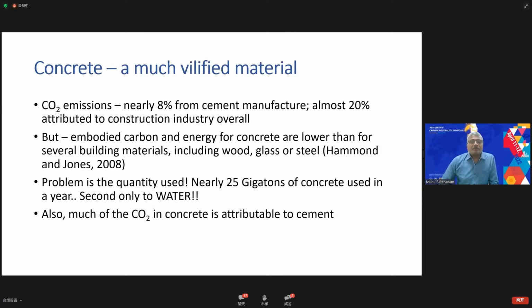The only difficulty is that we're using concrete in very large quantities. Estimates today put it at about 25 gigatons, making it the largest ever used material, second only to water. That causes the impact of concrete to be very large.